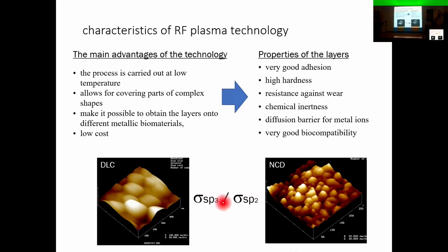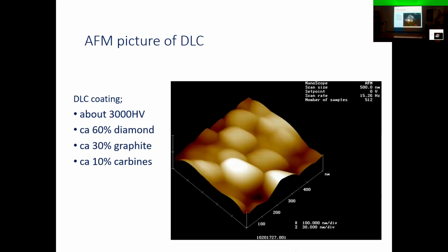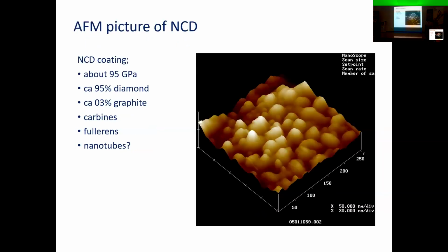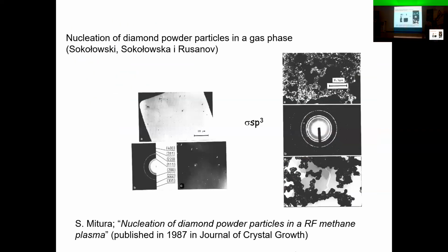But we can also obtain diamond-like carbon coatings, which are amorphous coatings. So especially it depends on the application. Sometimes it is better. You can also incorporate some other elements into the coating. So depending on what you need, you can obtain even increased antibacterial properties of the coating, for instance. So a DLC coating is about 60% diamond, 30% graphite, maybe some carbynes or other allotropic forms of carbon. NCD is almost diamond, but with some additions of other forms of carbon as well.